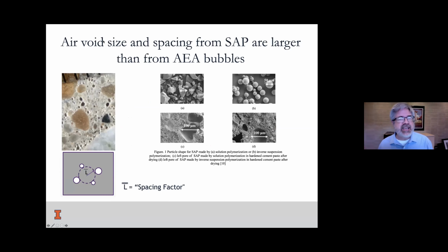The basic thing is the air void size from air entraining admixture and the SAP is much larger than air entraining admixture. These are just some illustrative pictures, and I don't have data to give a lot of size, but just take it as a truism that these voids from SAP are big and therefore have big spaces and therefore have limited ability to reduce freeze thaw stresses and degradation.